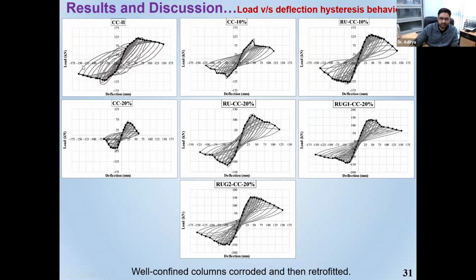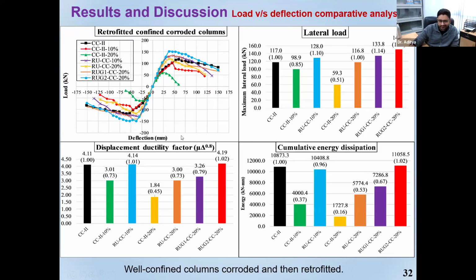This was a control specimen, then 10% corroded, you can see its performance has reduced, then again 20% it has further reduced. For 10%, when we are doing retrofitting with RU, meaning retrofitting with UHPFRC, you can see its performance has again jumped to almost the control one. Similarly, for 20%, we can see the response has increased. Then G1, that is 1 layer of GFRP, and G2, that means 2 layers of GFRP. So the response keeps on increasing as we keep on adding the amount of retrofitting. Okay. Same goes with other parameters.